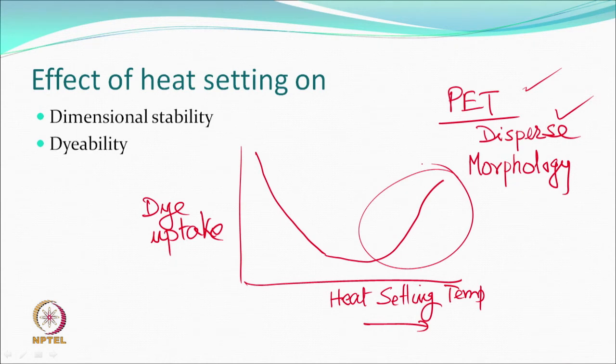The internal crystalline morphology has an effect on dyeability. Mechanical properties can also be affected: if disorientation takes place, tenacity may decrease slightly; but if you stretch and then heat set, tenacity can increase. Mechanical properties depend more on orientation — more orientation along the fibre axis improves tensile strength; more relaxation allows tensile strength to decrease slightly, but not significantly.